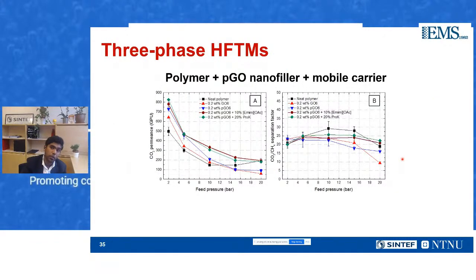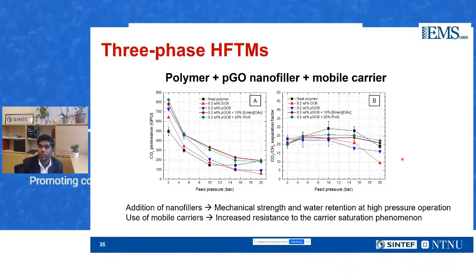So we expose this system also to CO2 methane studies, where we are increasing the CO2 concentration on the feed side to 40%, and also increasing the pressure from 0 bar or 1 bar to up to 20 bar on the feed side to see if it has any effect. The addition of nanofillers is definitely proving positive because the mechanical strength of these membranes were quite stable until 20